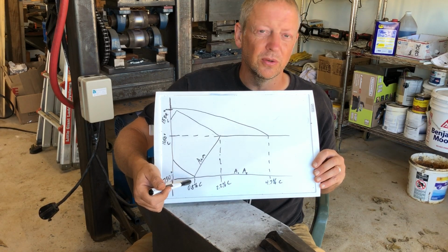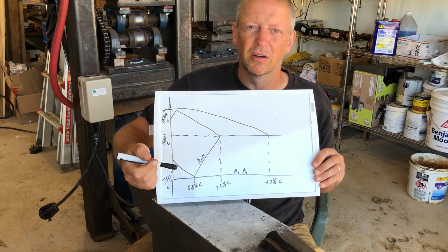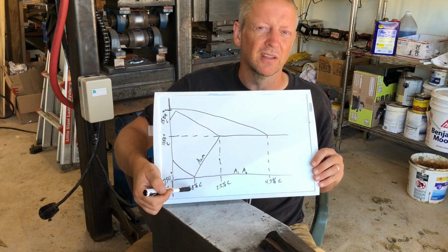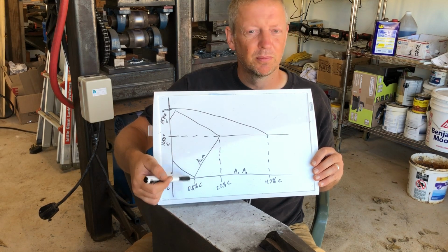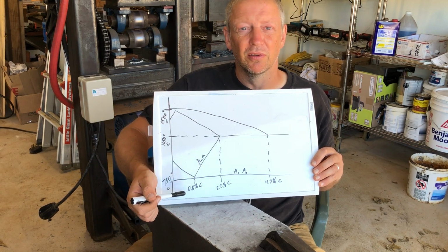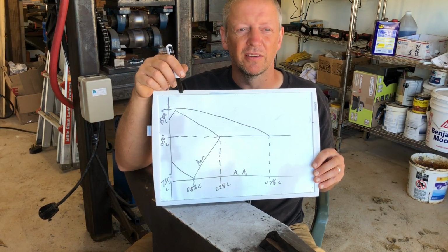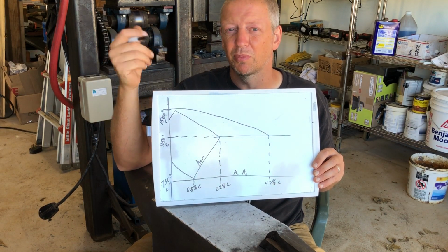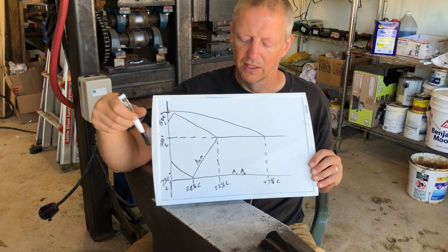And you will start to have the carbon, it's no longer soluble. It is getting rejected. It's getting kicked out. So what you get essentially is pure iron and then layers of pure carbide. This creates kind of a pearlescent appearance in micrographs, thus pearlite.